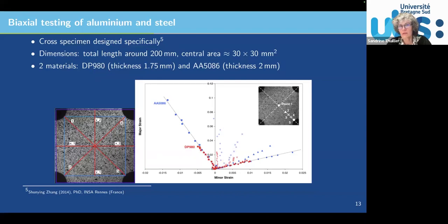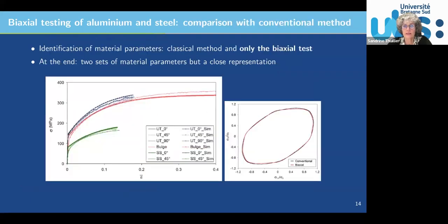I know it may not be familiar to you. It's a French anisotropic yield criterion involving 12 parameters. So we used such a criterion. The model was calibrated from one cross-shaped specimen in biaxial loading, and then we performed numerical simulation of a tensile test, a shear test, and a hydraulic bulge test, and compared with experiments.